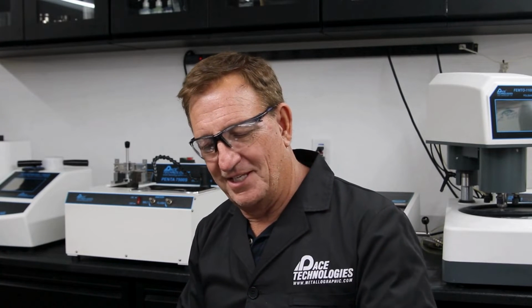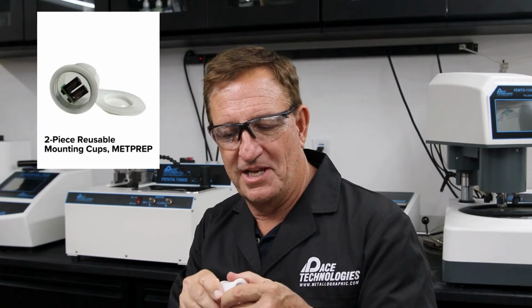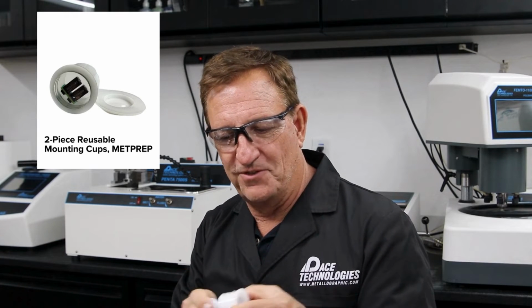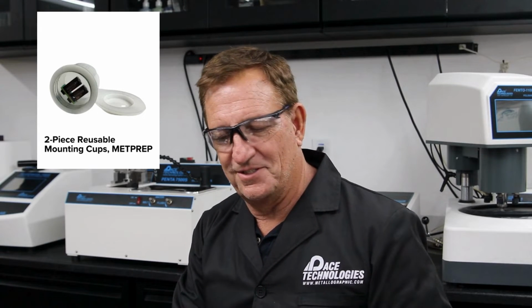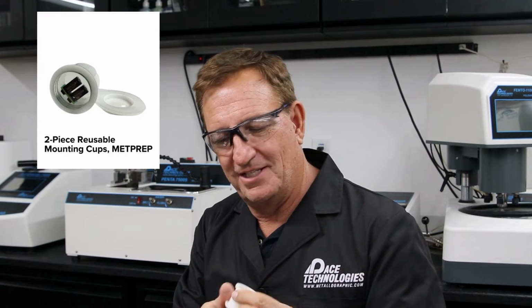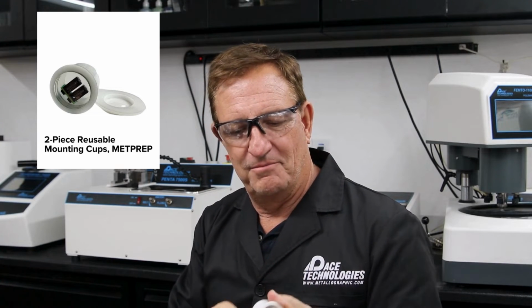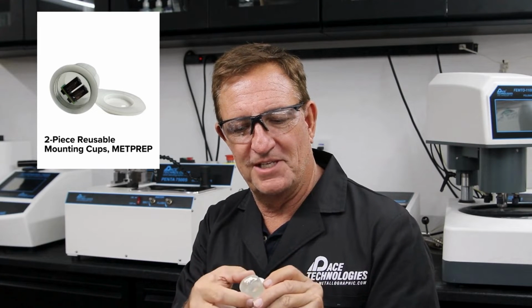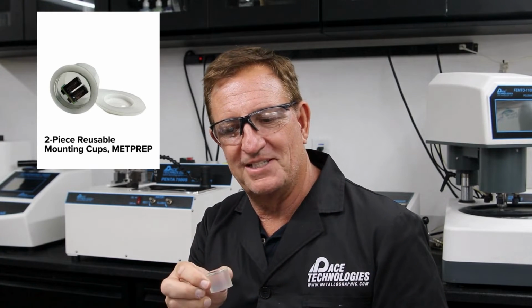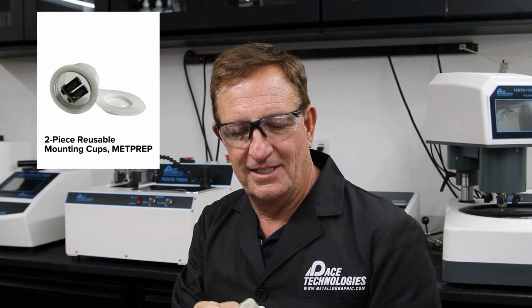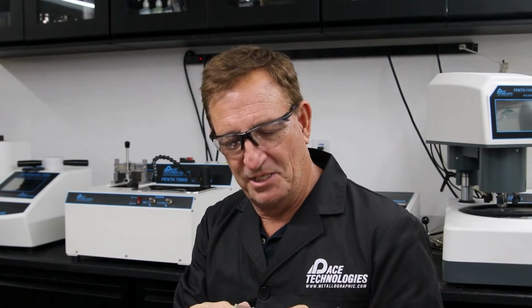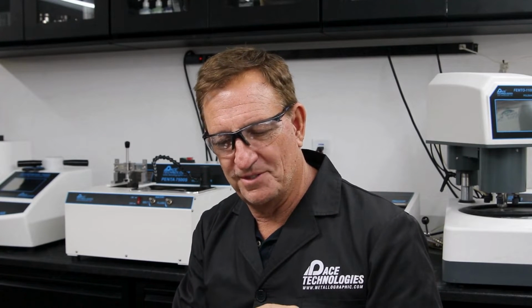We also have these two-piece molds which actually come apart so that you can remove your sample. Here's an example. This is an acrylic that's been mounted into it. Basically, pull out the bottom piece there and it pushes up through the top. So it's tapered a little bit, but this is a way to have reusable molds. The rubber molds are also reusable, but they do have a tendency to break down a little bit faster than these plastic two-piece molds.